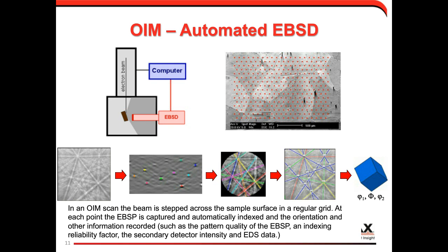And then with automated EBSD, what we do is we define a measurement grid, as shown on the top right there, and we just define an area and a step size to measure from. At each point, we go through the flow shown on the bottom there as we get a diffraction pattern. We process it in those middle two steps, finding the position of the diffraction bands via some image processing algorithms. Those bands correspond to different crystallographic planes. So by knowing the spatial distribution of those planes, we can calculate the crystal orientation and the crystal phase present at each point.